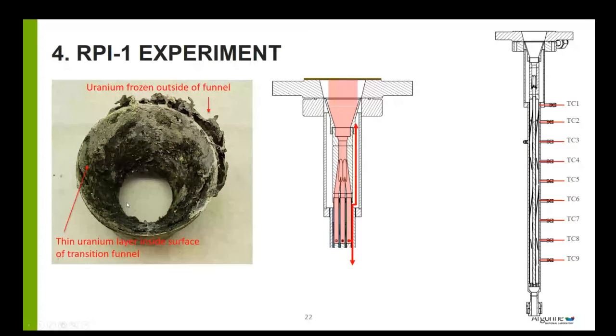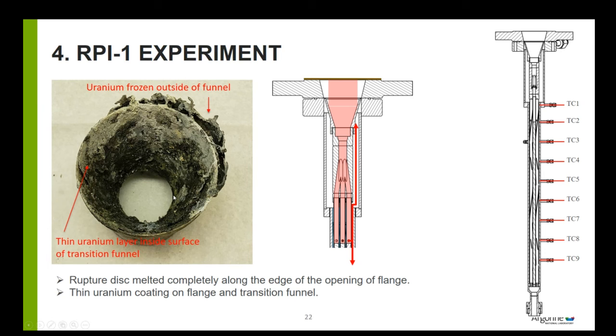So this is the picture of the transition funnel after disassembly. Same as the copper injection test, the rupture disk melted completely along the edge of the flange. And the internal surface of the flange and the transition funnel was coated by uranium. A thin uranium layer was found on the transition funnel, and no large chunks of uranium were found inside the flange or the transition funnel.